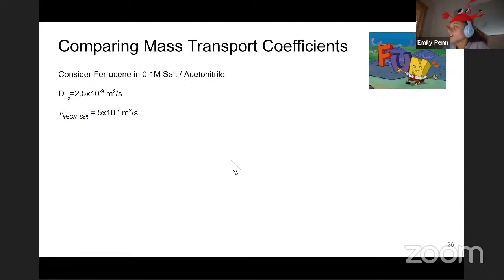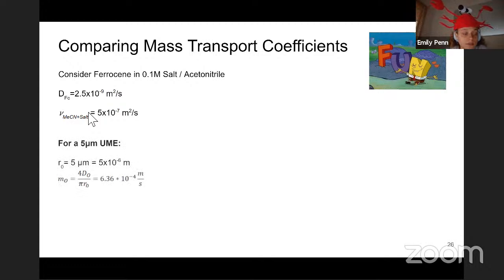Just a quick aside, I'll go through this really fast since we're close to the end of time. But it could be interesting to compare the mass transport coefficients for an ultramicroelectrode versus a rotating disk electrode. So if we consider a solution of ferrocene in a 0.1 molar salt solution in acetonitrile, we know some diffusion constant for ferrocene on the order of 10 to the negative 9 meters squared per second. And we have some kinematic viscosity for the acetonitrile salt solution. For a 5 micron radius UME, we can calculate the mass transport coefficient. And we get this value here, which is about 6 times 10 to the negative 4 meters per second.